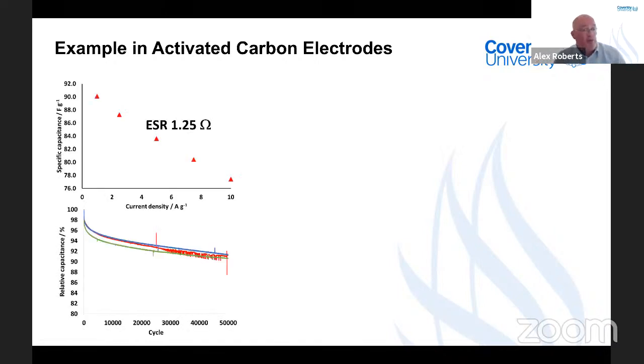So these are fairly large cells. I did all of my background work. I worked with my coin cells. I came up with some results that showed a reasonable equivalent series resistance, nice rate behavior, and a cycle life as good as I would expect in a coin cell. So I did my calculations and I thought, in my devices, I'm going to come up with an equivalent series resistance of less than 10 milliohms. So I was quite happy.